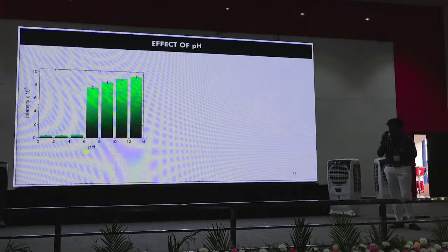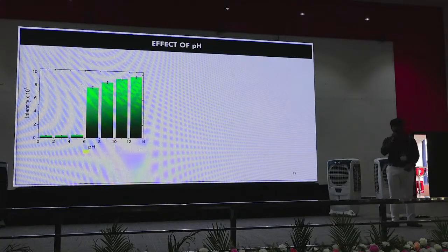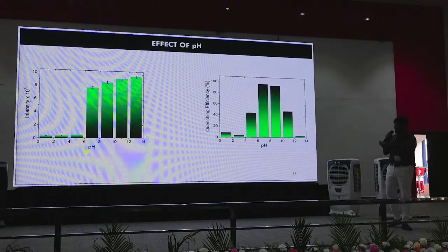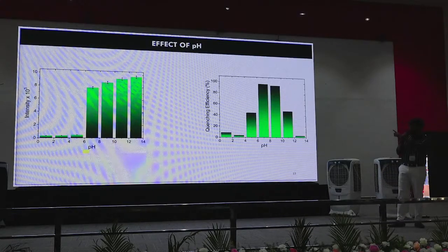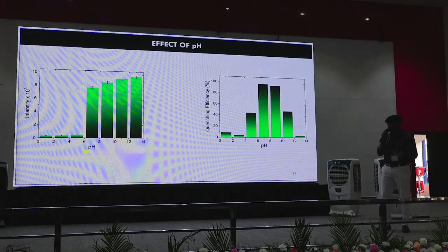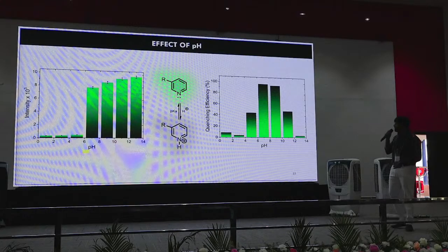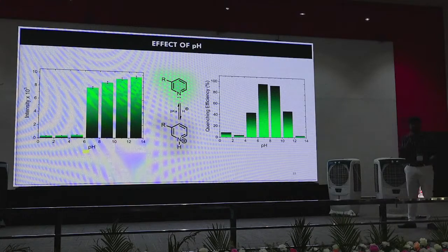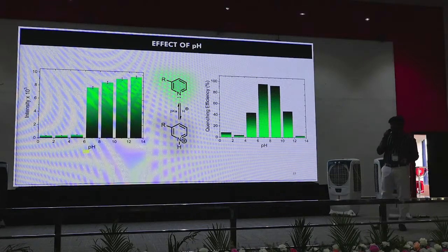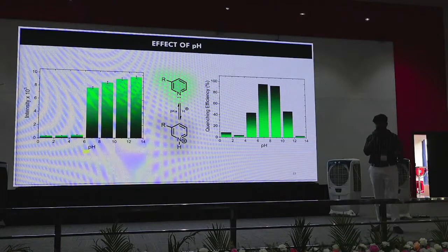And the effect of pH, since we are going to use this in practical applications, we just have to determine what is the effect that pH causes here. As you can see, in the acidic condition, the fluorescence intensity is very low, whereas the quenching efficiency in the practical region, that is from 7 to 8, is not affected that much. This might be due to our molecule containing pyridine; when we change the pH value, the acidic nature will affect the fluorescent intensity.